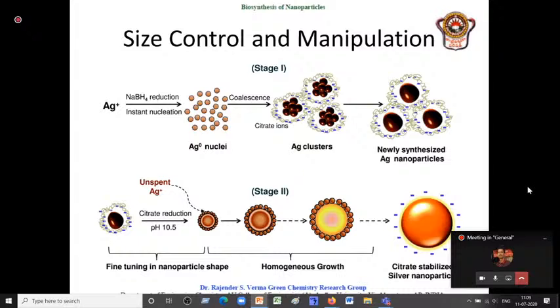But if you are using a precursor there, slowly this precursor will help in stabilizing these nanoparticles. It will control the growth and they will be stabilized. In the sense, every silver particle will be surrounded by some stabilizer or precursor, so that the required size of the nanoparticle will be maintained in this particular context.